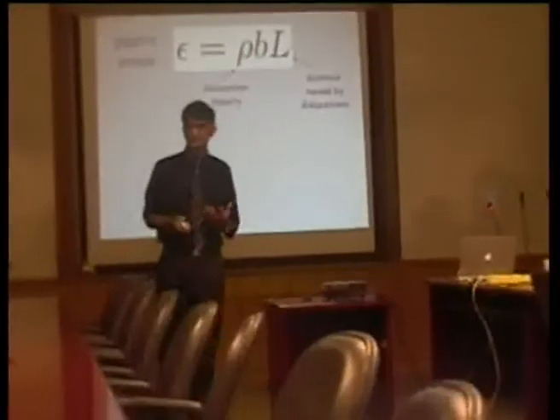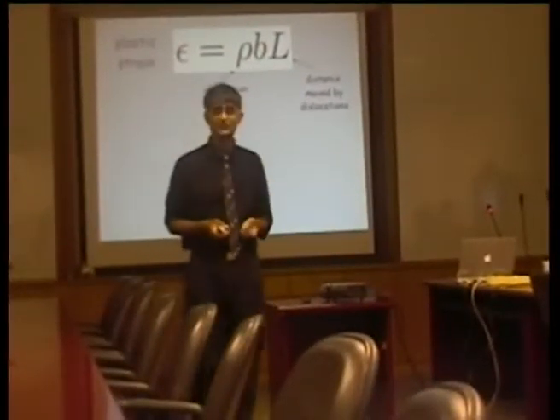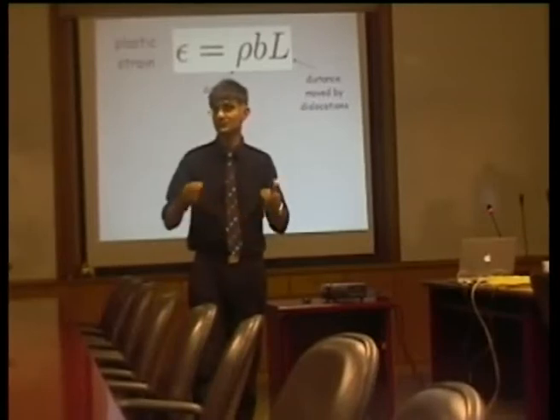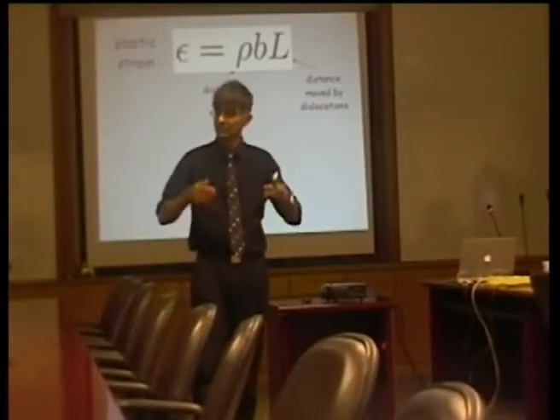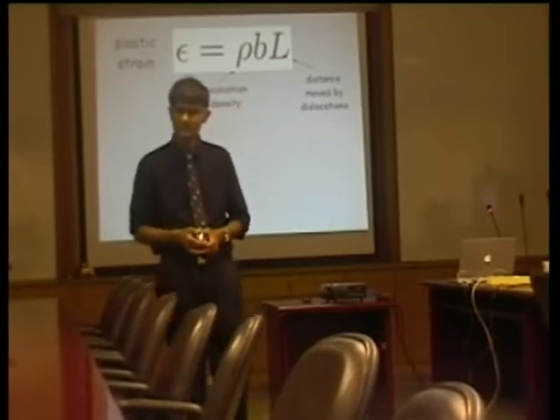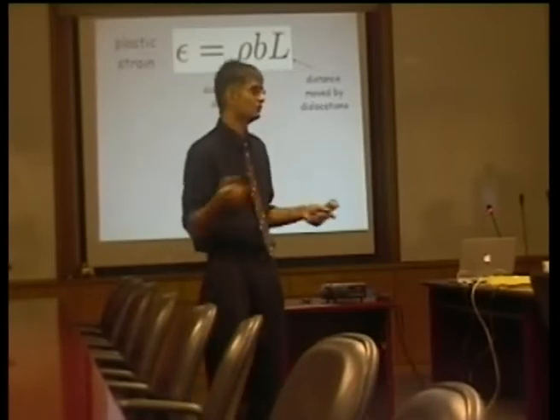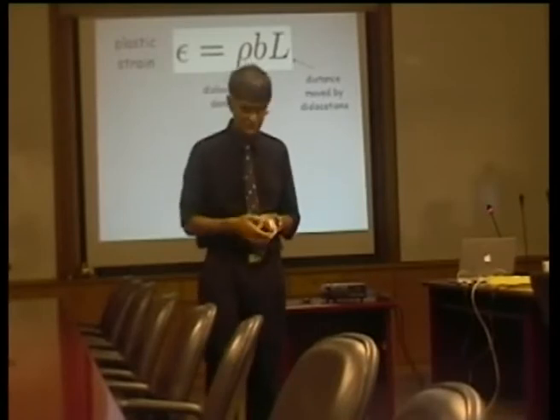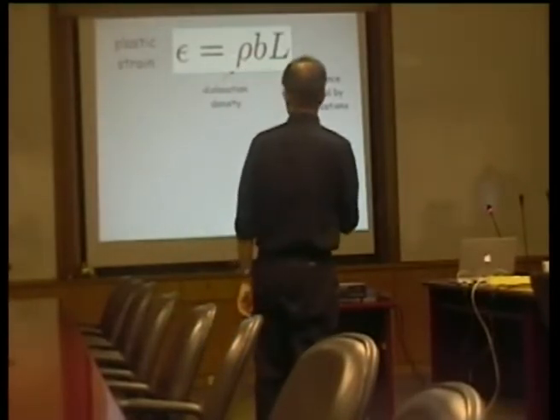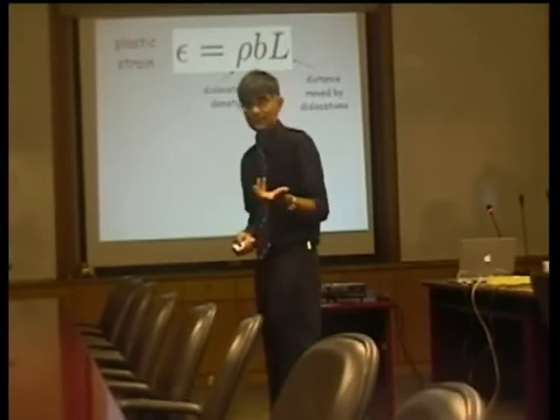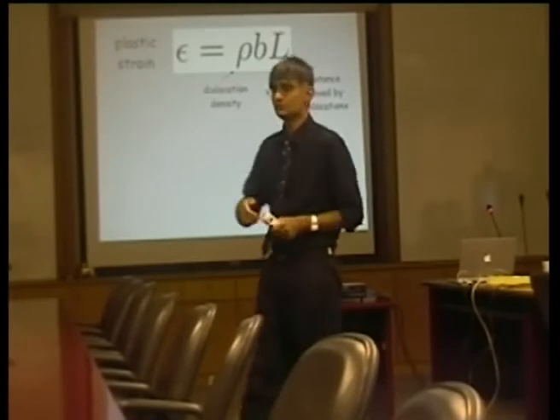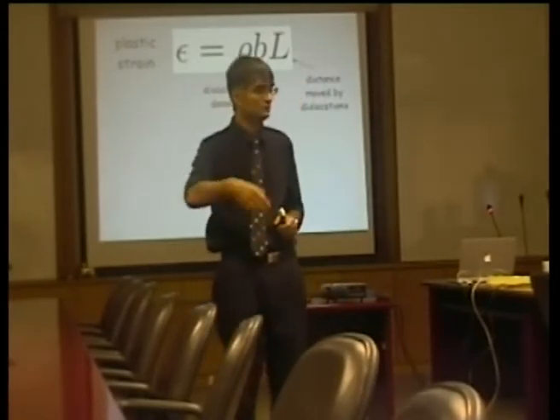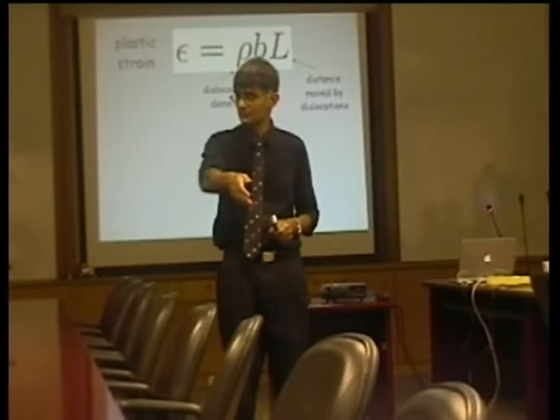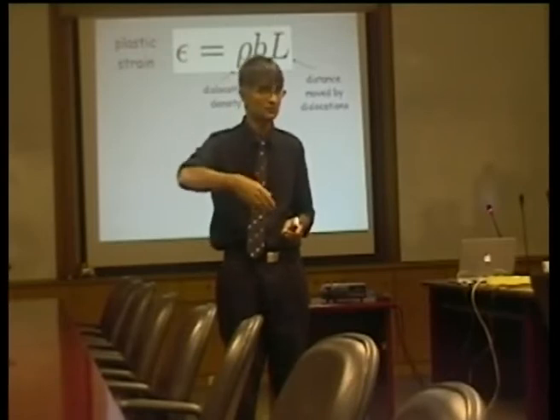Okay, so let's now develop a physical theory which predicts when we should get mechanical stabilization, when plastic deformation in the austenite should retard the martensite transformation. Well, first of all, let's imagine we have some dislocations in our material, and the dislocation density is rho here. And the Burgers vector of the dislocation is b. And L is the distance which a dislocation can move before it hits an obstacle. So it's the free path that a dislocation can move.